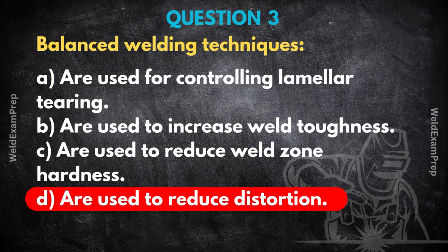It can be. It also often involves careful control of heat input, obviously. And in some cases, especially on large structures, you might even have two welders working simultaneously on opposite sides, literally balancing the heat input and stresses in real time. Wow. The whole point is to prevent that uneven heating and cooling, that localized shrinkage, which leads to warping. You want to keep the component dimensionally stable.